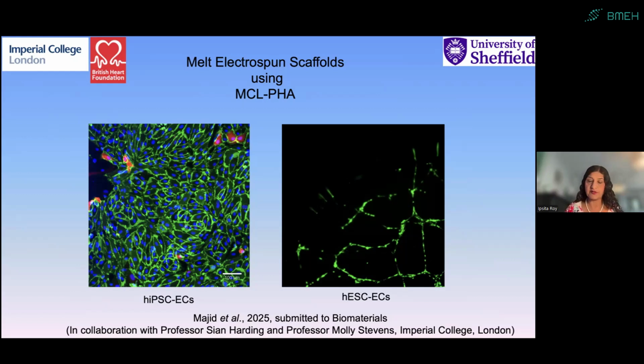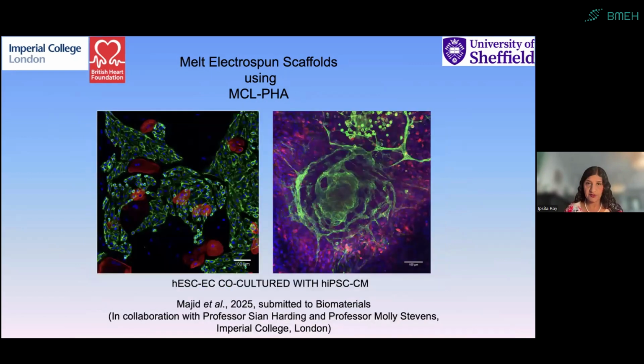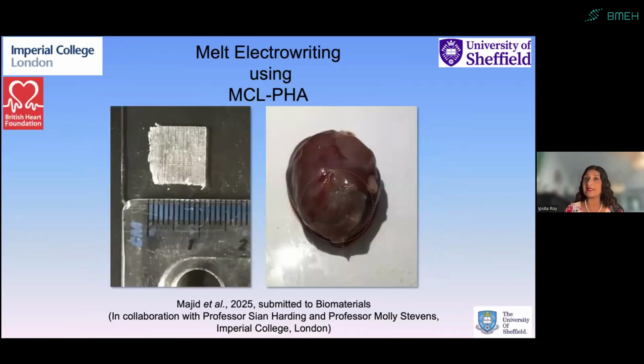We, of course, understand that any patch needs vascularization, which is a major challenge for tissue engineering. So what we did was we tried to grow iPSC, again, the induced pluripotent stem cell derived endothelial cells, and observed whether we could get some nice vascularization. And you can see here that the endothelial cells grew on the medium chain length PHA and also resulted in vessel formation. We then combined the two types of cells and we created the patch.